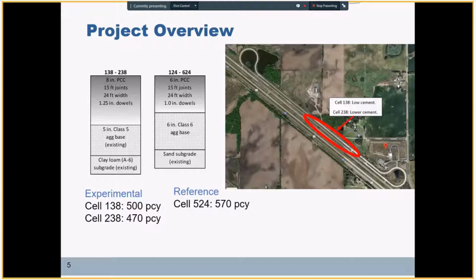We are trying in this project to compare the performance and the data as much as we can with a reference cell, cell 524, cast with concrete with 570 pounds of cementitious material. This section was also constructed in July 2017, and the main difference is that for this cell we have a pavement thickness of 6 inches and we are using 1-inch diameter dowel bars. So this section hopefully can serve as a reference for us to compare the in-situ performance and material properties as much as we can.